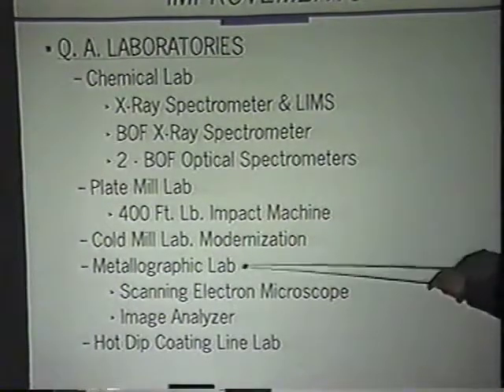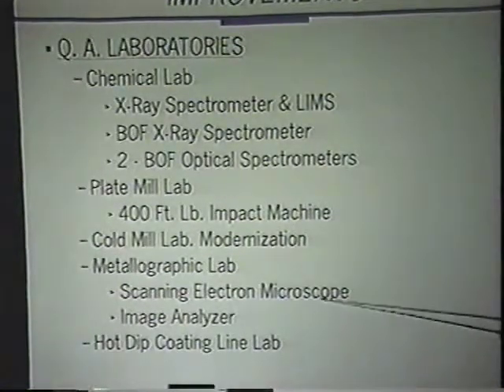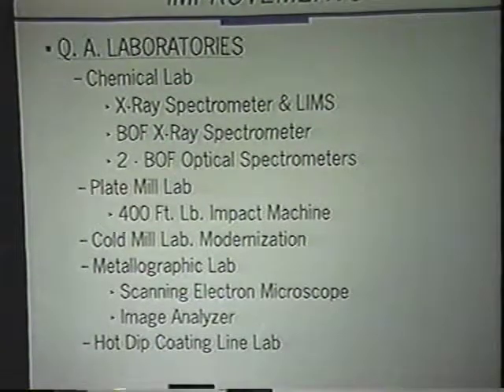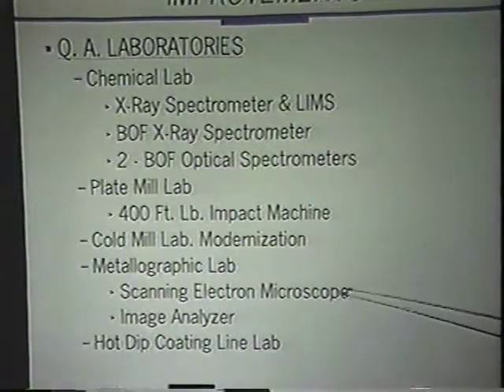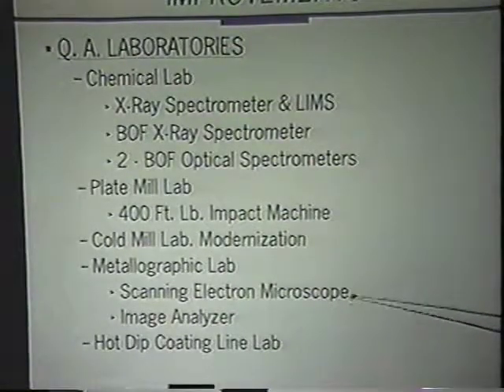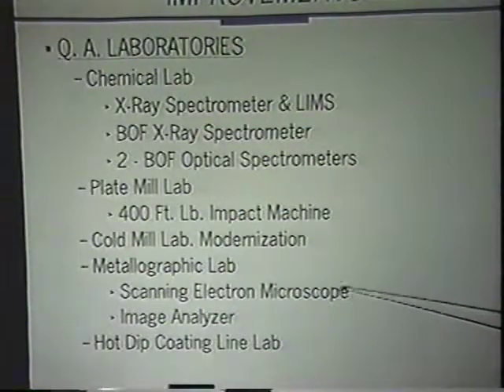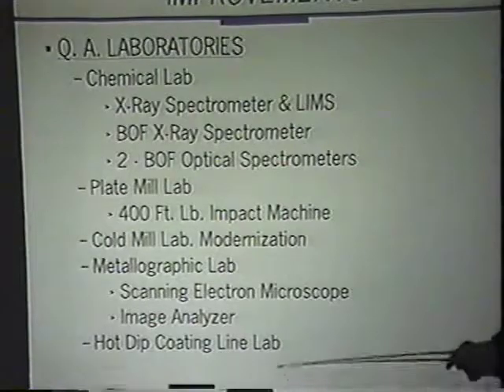In our cold mill, we put in a metallographic lab. We bought a scanning electron microscope. As we're getting into some sophisticated coatings, we needed a piece of equipment that can quickly measure the percent alloy layers. In previous years, we had to send these samples back to our Homer research, which might take a week or so to get the analysis. Now we can get it very quickly. We also put an image analyzer in there, and we put a new lab in when we started up our hot dip line.